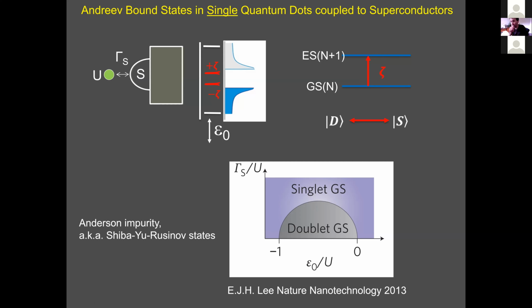And when we do transport measurements, we send current through the dot. And so what we do is we go from n to n plus 1 electrons constantly. So we have a transport resonance whenever our voltage bias matches this energy difference, which is equal to zeta. So this allows us to map out the spectrum of Andreev states by passing current. Voltage will just give us the energy of Andreev states. And also you can see from this that when we follow this line here, the topological phase transition, quantum phase transition line, then the energy difference between doublet and singlet is 0. So the energy difference between these blue lines is 0, and we will have a 0 bias peak in our spectrum.